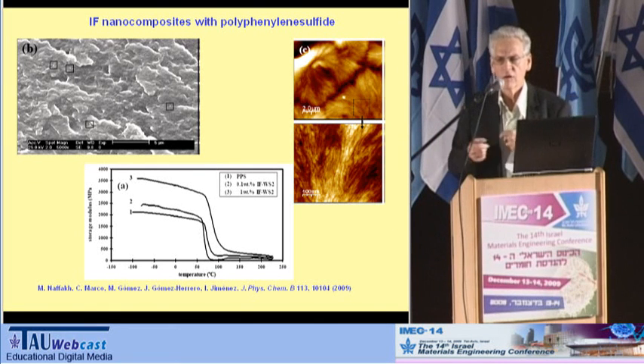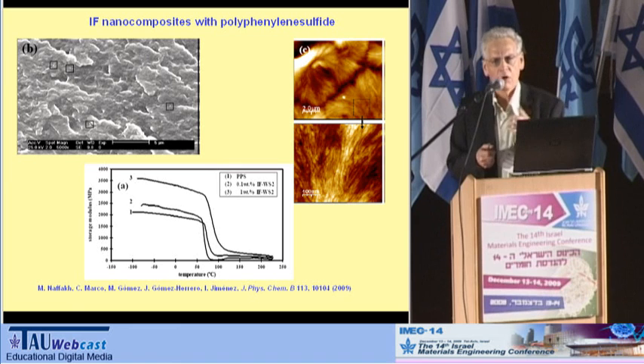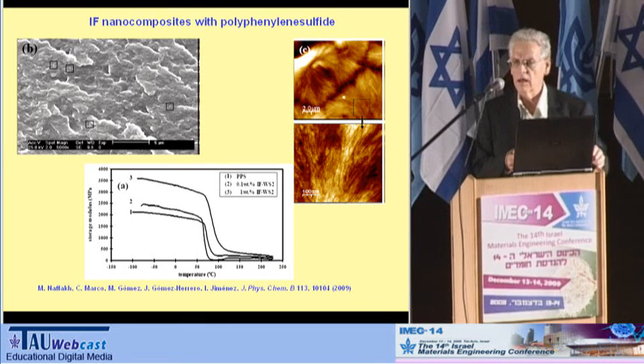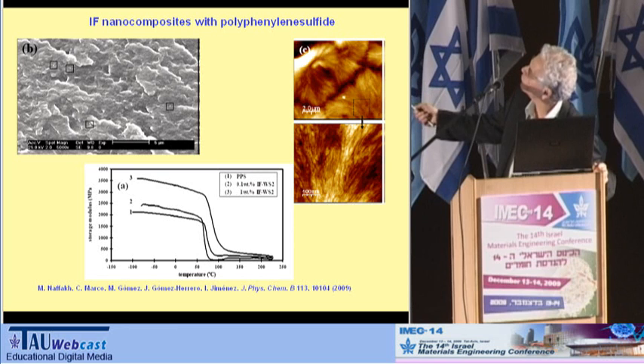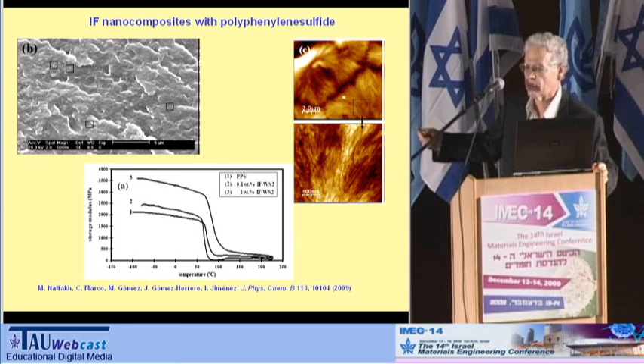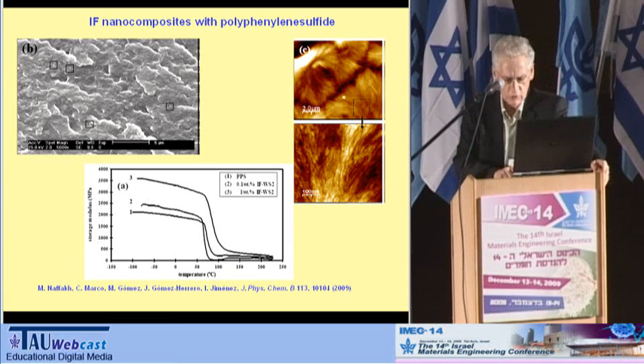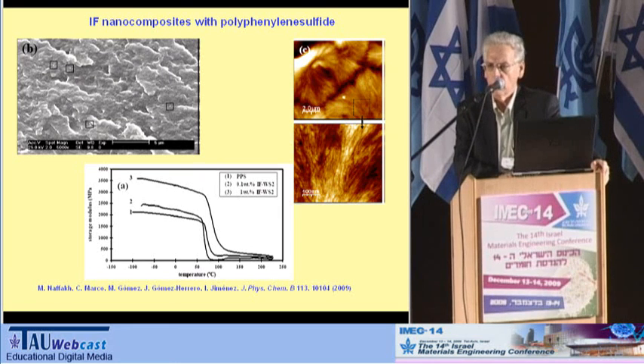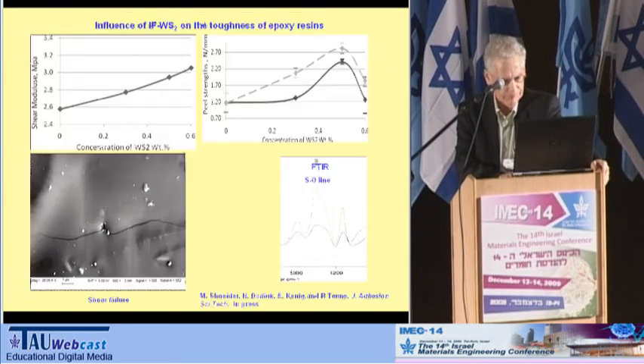Of course, there is a chemistry. There must be some chemistry ongoing between the nanoparticles and the polymer. But this problem has to be elucidated in greater detail. Anyhow, you see the nanoparticle and you see the crystallization around this nanoparticle, so it serves also as a nucleation catalyst for the polymer, for the thermoplastic polymer.